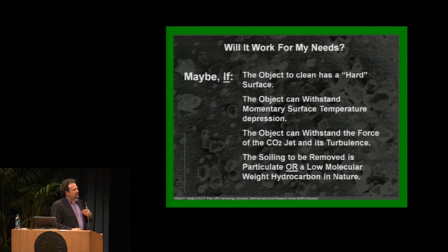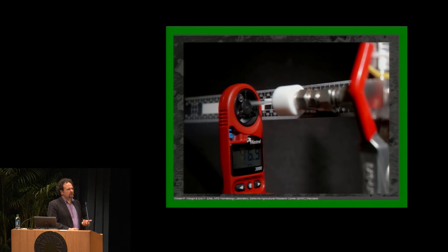The other thing you have to take into consideration, as Robert noted, is, can it put up with both the force and the turbulence generated by a jet stream? It is truly a jet. I did a little measurement with an inexpensive weather station. This is a jet that's generated out of a fresh tank. You can see how thick it is. This is gas only. This is not a liquid generated stream. And the meter, if you can see it, that's 46.9. Well, what are the values? That's meters per second. So you get an idea of how fast the air is moving.